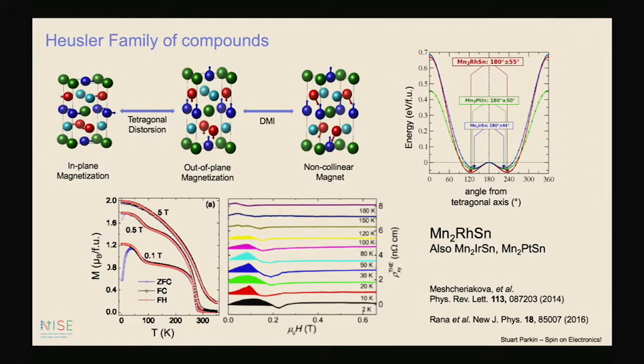Heusler materials. And as she mentioned, my interest has been for a long time Heusler compounds which have large anisotropies, so that the magnetization wants to be perpendicular to the tetragonal plane of certain of these tetragonal Heusler materials. And it turns out these materials have a certain symmetry, D2d point group symmetry, that should stabilize anti-skyrmions. And indeed, that's what we see in these systems. I want to discuss those briefly.